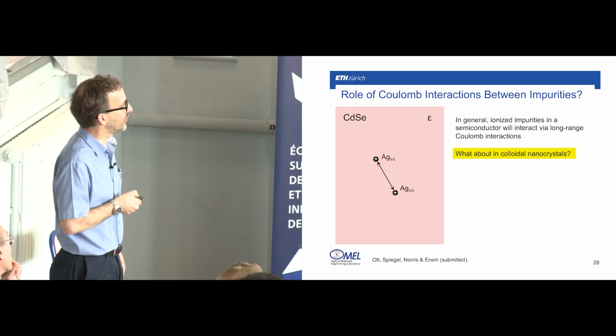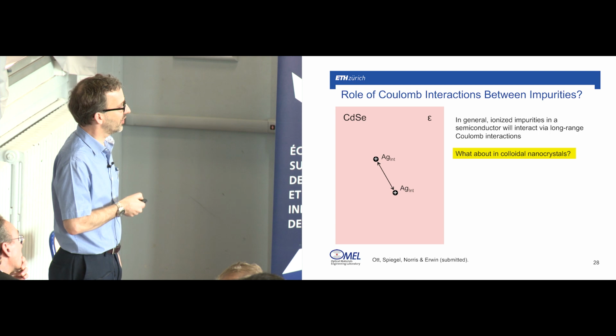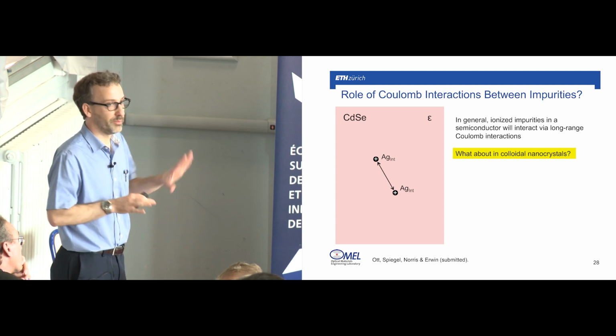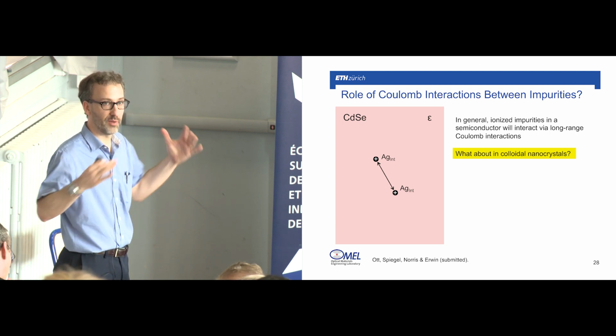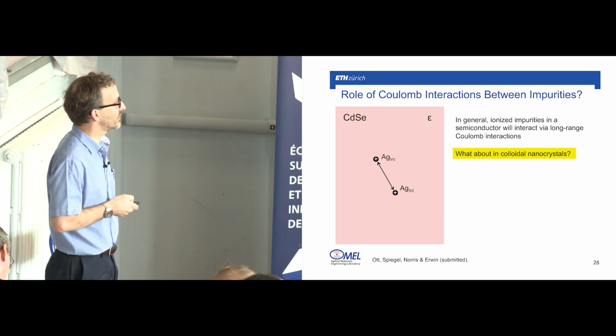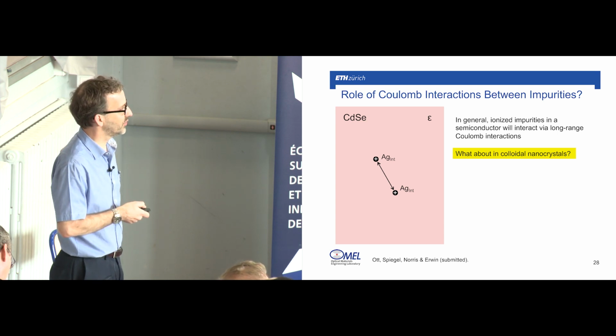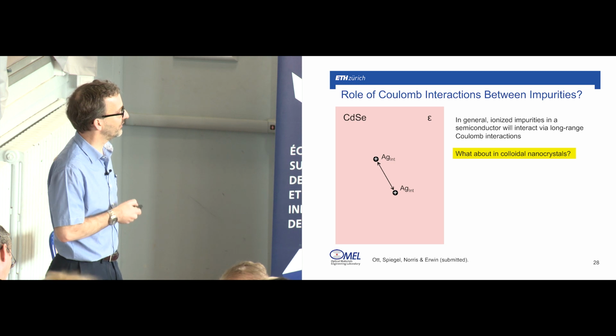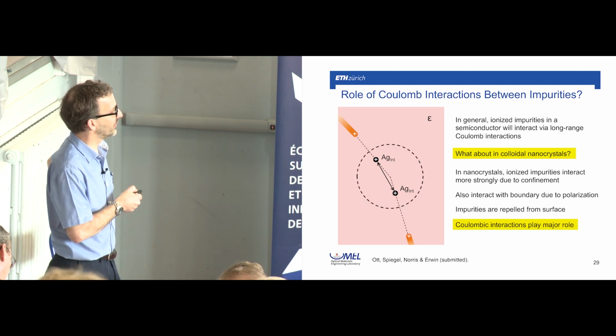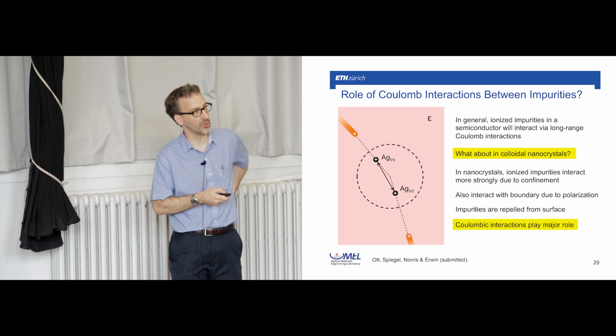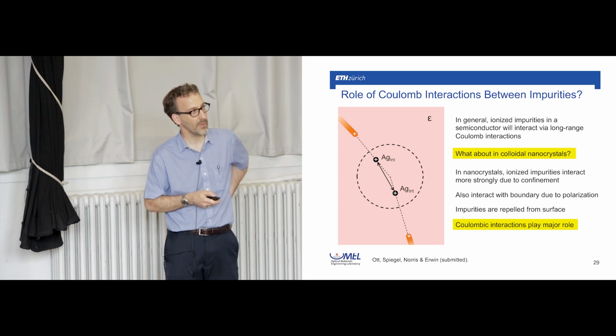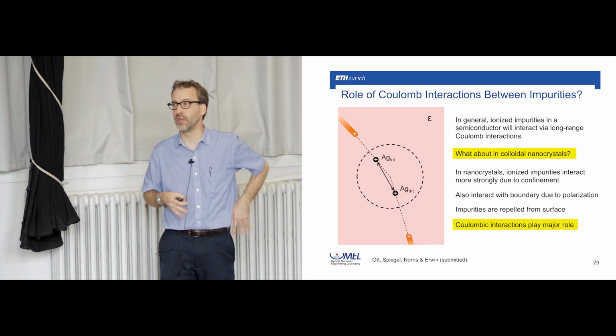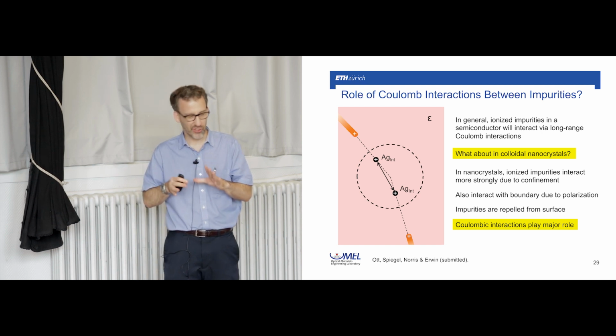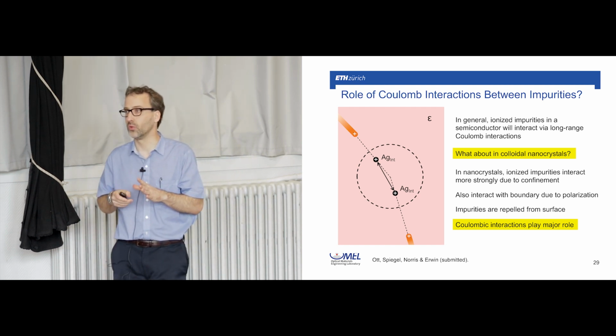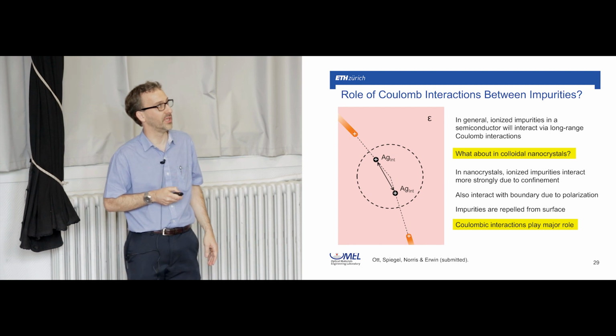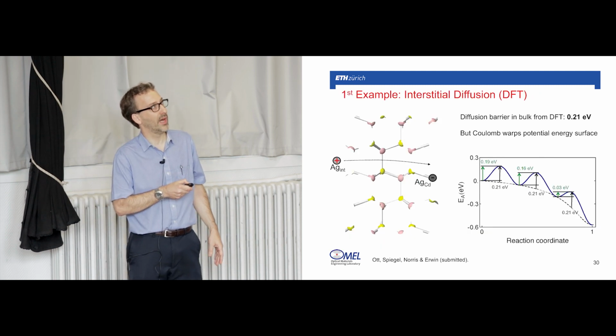And on top of that, I told you about Born's old ideas about charge solvation. These will be repelled from each other and from the surface. So all of these Coulomb interactions between the charged impurities turn out to be everything. And you can model the repulsion from the surface by image charges, and so you can do all of this quantitatively. So these Coulomb interactions play a major role. In fact, cation exchange would not happen without these Coulomb interactions, as I'll try to show you in the last few minutes here. So, two examples of why these interactions are important.